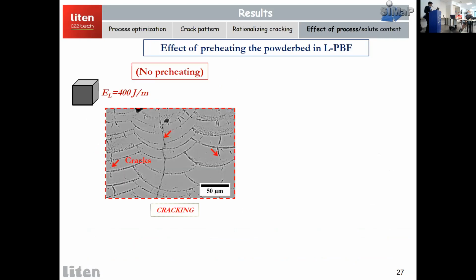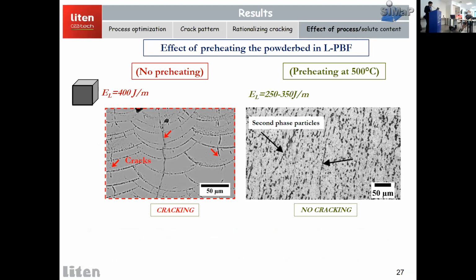Since just playing with powers and speed was not enough, we shifted our attention to preheating of the powder bed, because in the literature, it is reported to mitigate cracking. So here is a microstructure where for a particular linear energy density, in our case with no preheating, we get cracking. But for a similar linear energy density with a preheating of 500 degrees Celsius, this is from the literature, we end up having no cracking. The difference we have observed is the primary dendrite arm spacing.